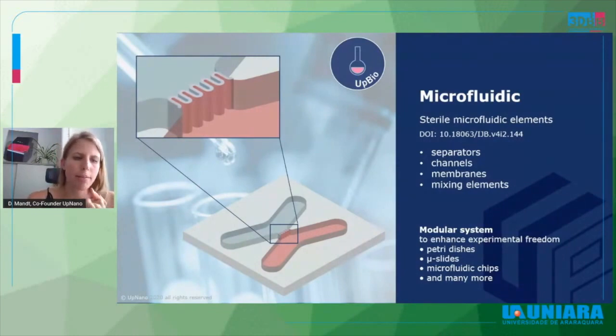Already the PEGDMA casting of the chip was done under the laminar hood, and also all the preparations of the material were done under sterile conditions. Then the material was washed away and the cells were seeded. Also, pretreatments of the chip or the materials are possible to have a better cell adherence. All this can be done again in sterile conditions and also after the printing process. While printing, as I mentioned before, there is no repetitive material application, so all the material needed for the whole printing process is already there, either in your well, in your microfluidic chip, or in the vat you place on top of your objective. Therefore, the microfluidic chip is an ideal setup to do so.